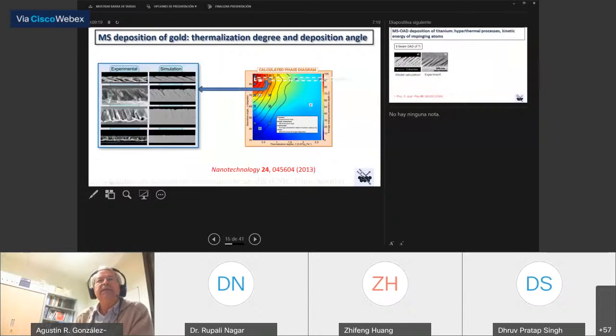However, if we move in this area where we keep the same deposition angle, but we move along the thermalization degrees, you can see here that we can move from this situation to this one, which is the one which is typically considered of an oblique angle deposition regime. But if we don't control sufficiently well the thermalization degree, we will get this other structure that you can see there. And these are due to this difference between the transport properties of the particles between the target and the substrate.